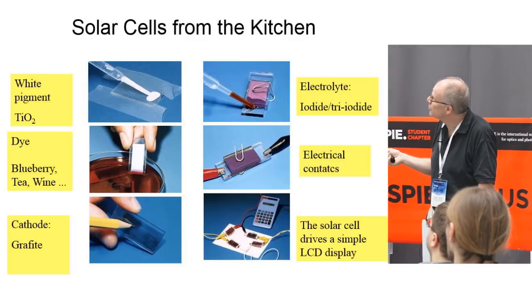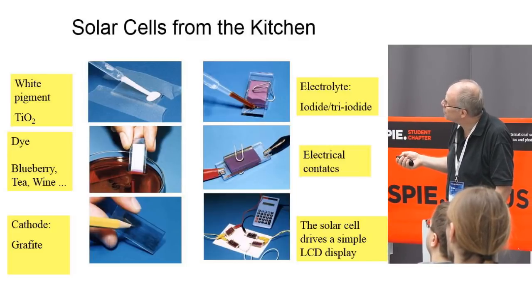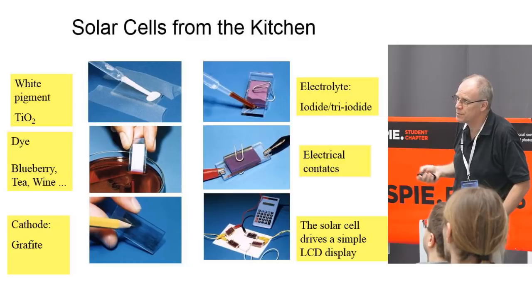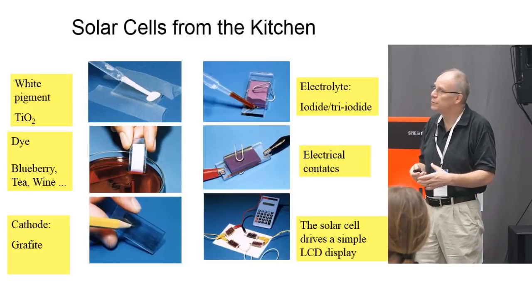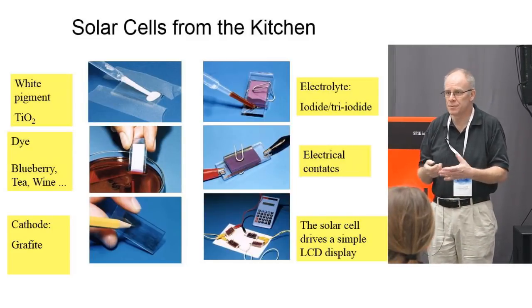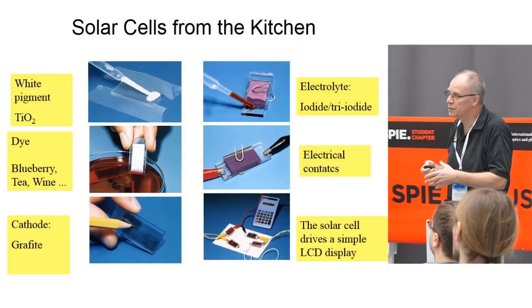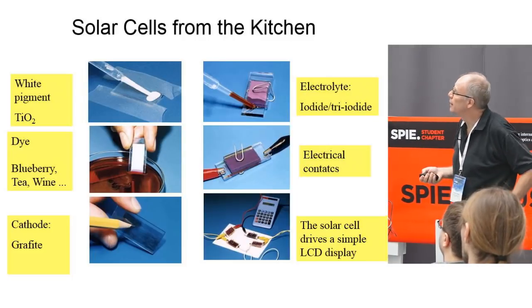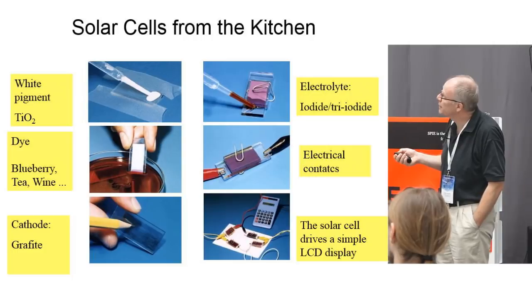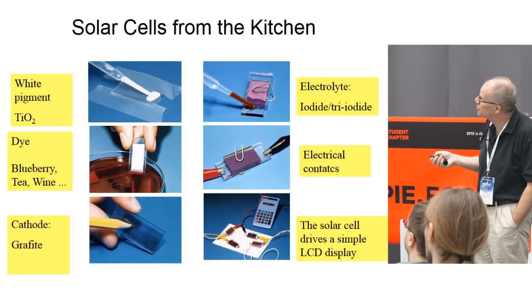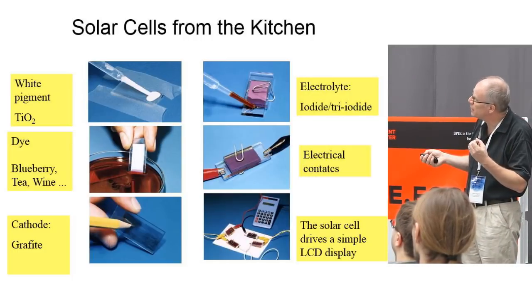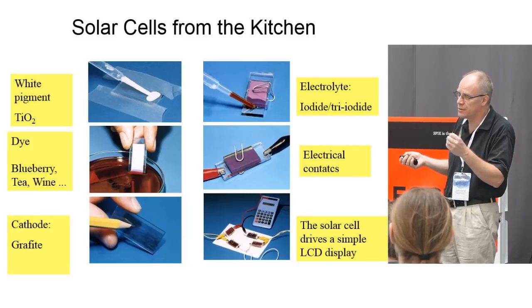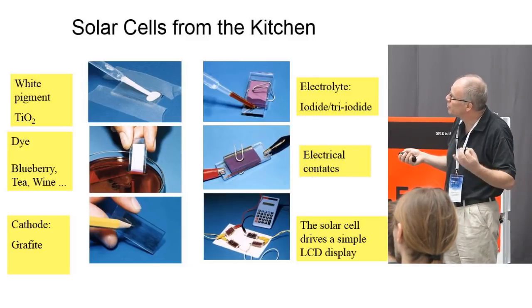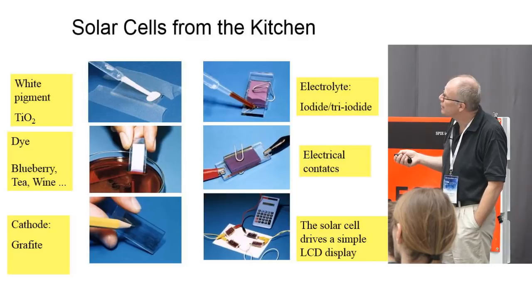and deposit it. You then take it into a step here, which is a sintering step. So you have an oven or a Bunsen burner in your chemistry lab and so on. You typically need 400 degrees for half an hour. And then you sort of bake it. And then you have a TiO2 layer, which, you will see later, is a porous system, high surface area, nanoporous electrode. And then you dip it in.